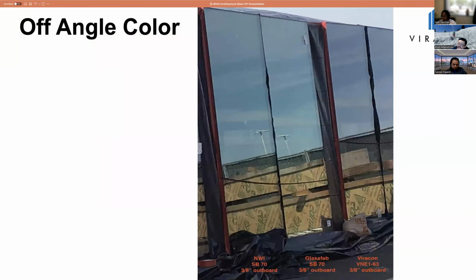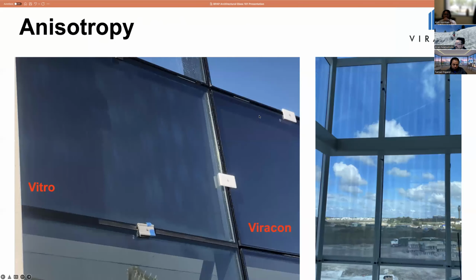And what's really noticeable in the difference is when you get off angle, the SolarBan 70 really starts to get green on you. Whereas with Viracon, we paid very close attention when we developed this coating to stabilize any off-angle color. And the main reason, on the project that we were called in to bring mock-ups on, was because of anisotropy. And you guys are definitely familiar with anisotropy in Southern California anyway.